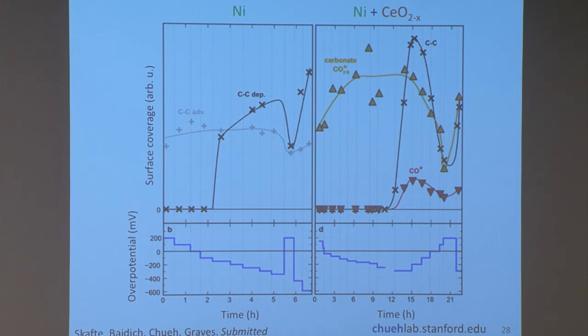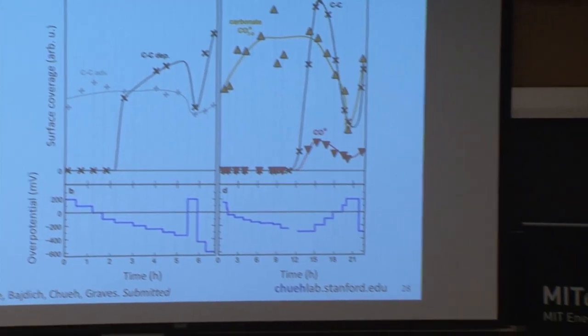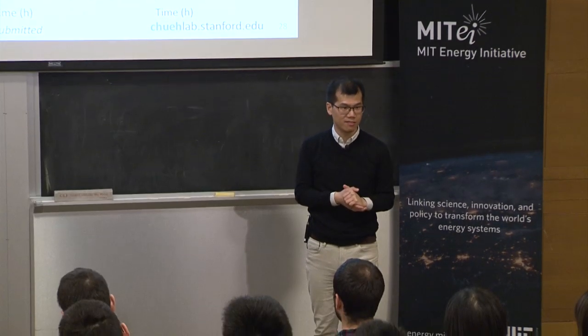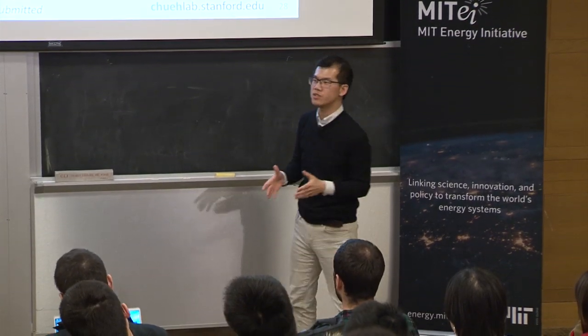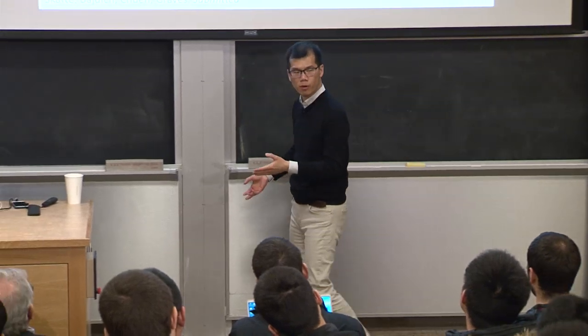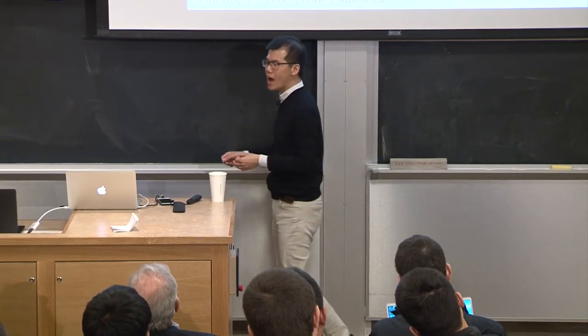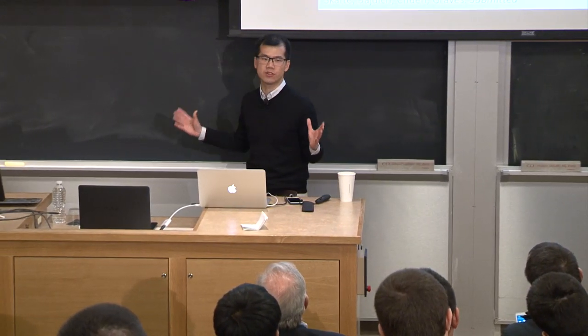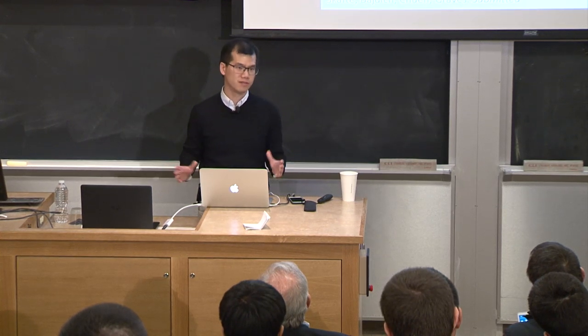I think this is the challenge. But you're right, just looking for carbon is pretty straightforward. But looking for these reaction intermediates, this is why we knew that the model is probably correct, because we can predict the stability of these intermediate species. And they are the key, right? They are the key to avoiding carbon from depositing, because we're trapping the carbon in carbonate, if that makes sense. So I think the short answer is yes, you can do it without the in situ approach. But having the dynamical aspect of materials just speeds up the understanding process very much so.